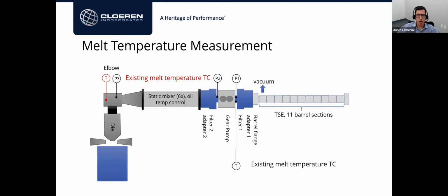So this is a simplified layout of this PVB process. It's a twin screw extrusion using a gear pump and static mixer. So it's a quite complex system, let's say. Then there is an adapter, and then the die, and the material is coming out into a water bath. So we measured the melt temperature as close as possible to the die entrance, and there's an elbow there, and that's what we used.